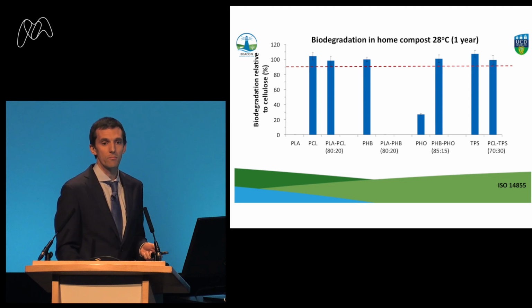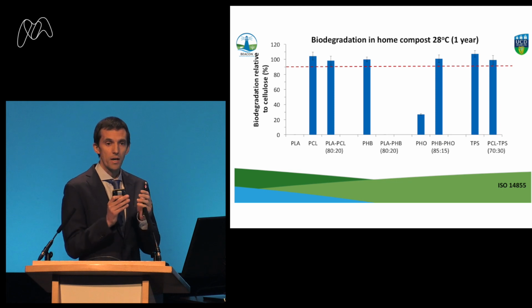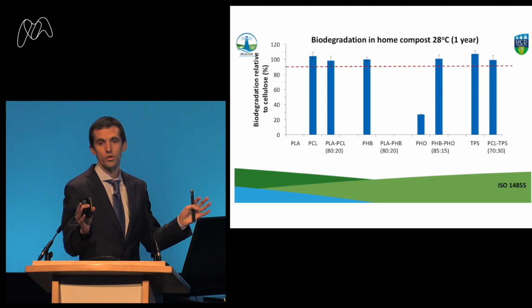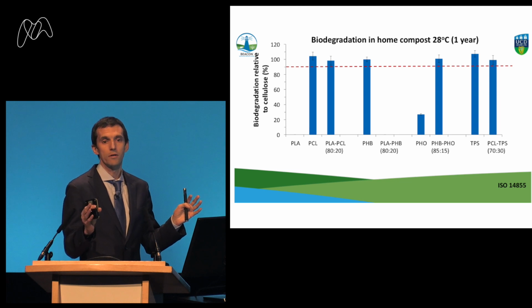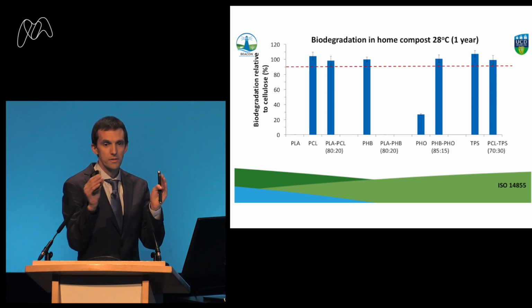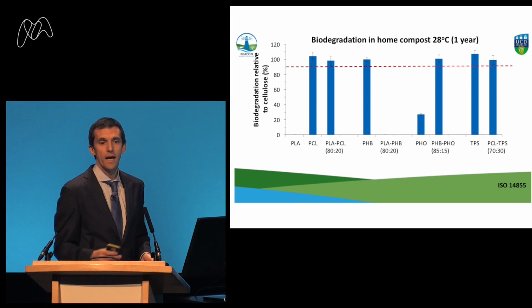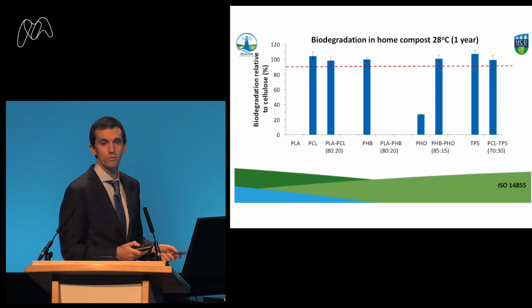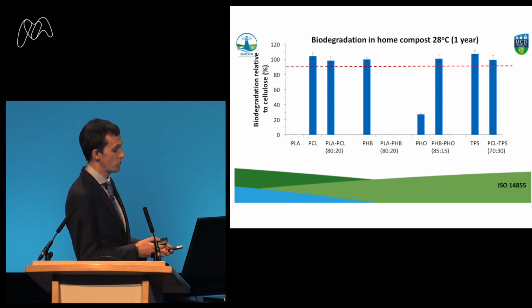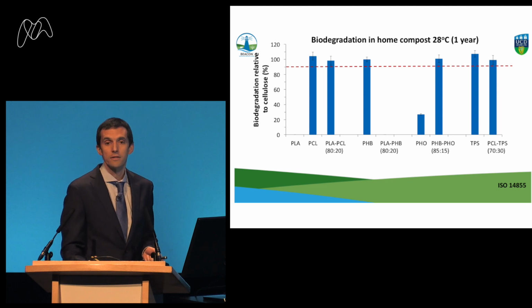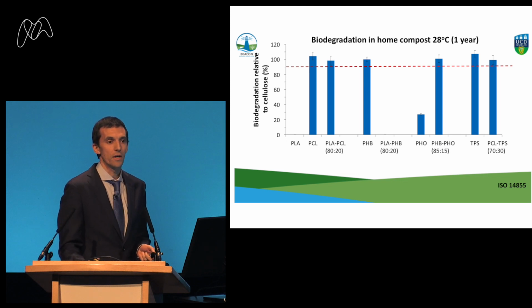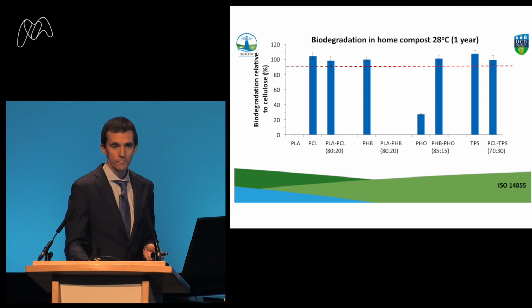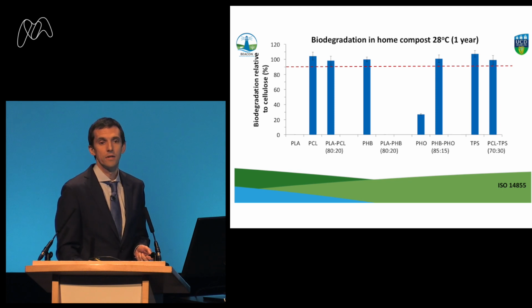We looked at scanning electron microscope images, and what we found was the polycaprolactone was evenly dispersed throughout the polylactic acid polymer when we blended it. And so you had pockets of biodegradation inside the PLA, and that was stimulating rapid degradation of PLA. We then said, could we do this with other polymers, like PHB, because PHB is also home compostable? But unfortunately not. When PLA is blended with PHB, the composite is not home compostable. We do not get the same distribution of the PHB throughout the PLA, and therefore it doesn't make the standard.